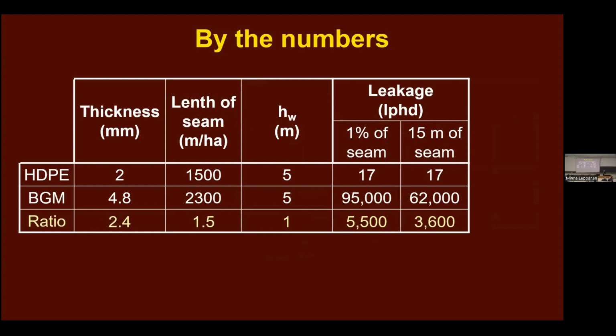And let's suppose 1% of the seam failed. For HDPE, the leakage would be 17 litres per hectare per day. For the BGM, it would be 95,000. For 15 metres of seam failure, it's 17 for HDPE and 62,000 for the BGM. Ratios of 5,500 and 3,600. So, caveat emptor.